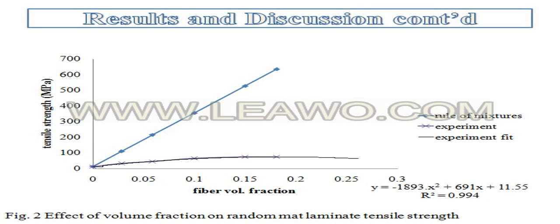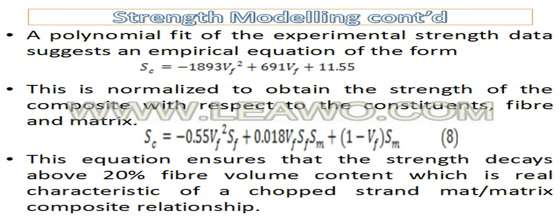Also, the tensile strength plot against the fiber volume fraction yielded a quadratic model which is presented in equation 8. This model ensures that the strength decays at above 20% fiber volume fraction. This is typical of a real fibre-mat composite.